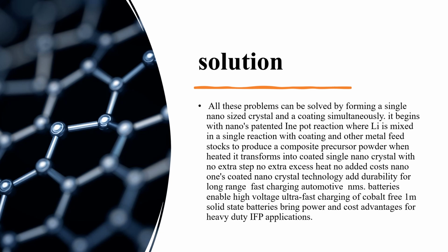It begins with a nano patented one pot reaction where lithium is mixed in a single reaction with coating and other metal feedstock to produce a composite precursor powder. When heated, it transforms into a coated single nanocrystal with no extra step, no extra excess heat, no added cost.